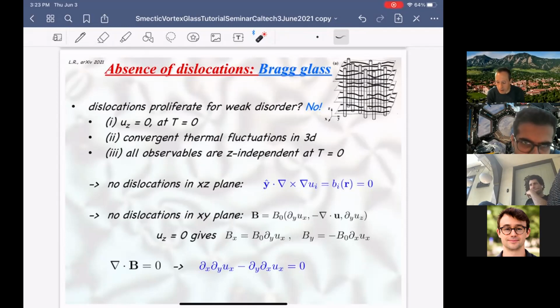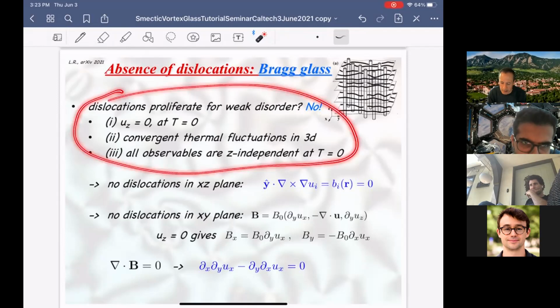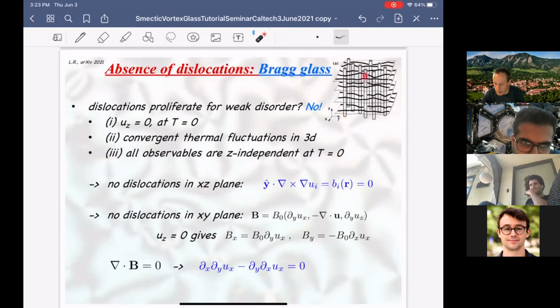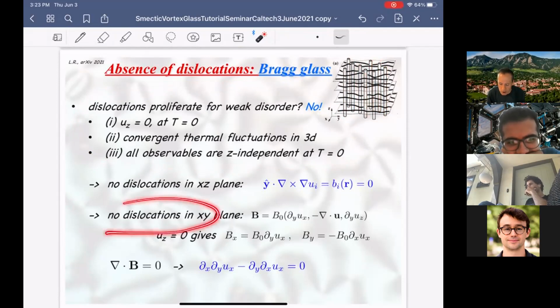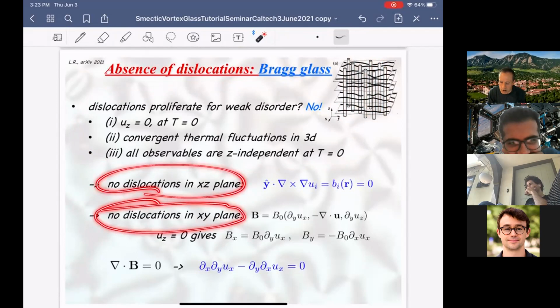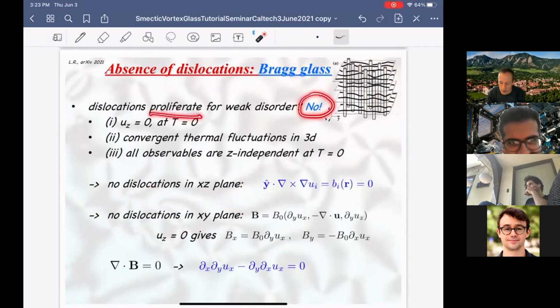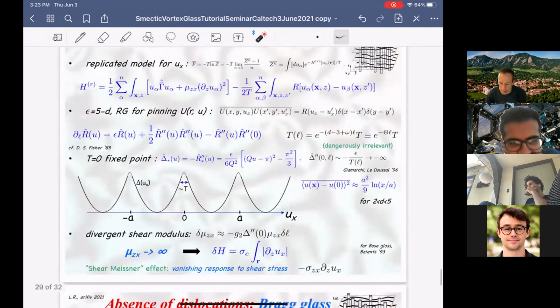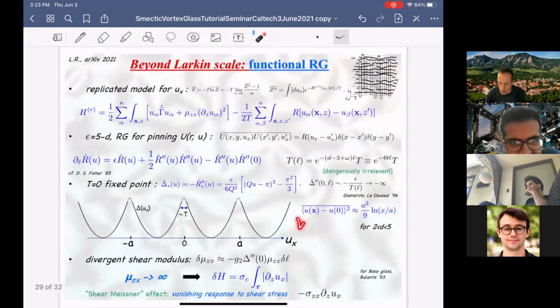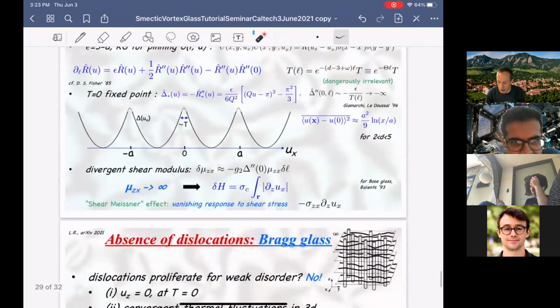But here, actually, the situation is much simpler. There's a set of ingredients that I list here, most important of which is that the columns are Z independent. Disorder is completely Z independent. And one can use that to argue that there are no dislocations in either the XY plane or the XZ plane. And so indeed, dislocations do not proliferate. I argue that this picture is in fact stable to proliferation of dislocations. So I believe this is the correct picture, even if you allow for the possibility of dislocations. For weak enough disorder, they do not proliferate.